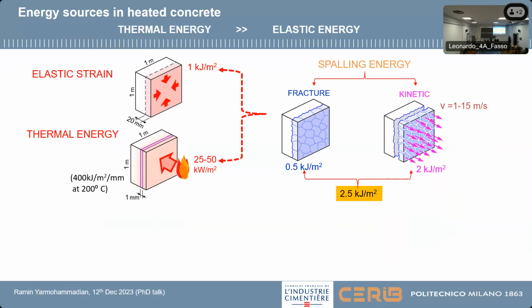So what are the alternatives? What are the options to provide this energy for such an explosive event? The first one is elastic strain, which is thermal stress. For the elastic strain, the whole energy which is stored in the whole concrete cover is 1 kilojoule per square meter. So 1 kilojoule per square meter is not enough for that high energy, so we need to go for an alternative.